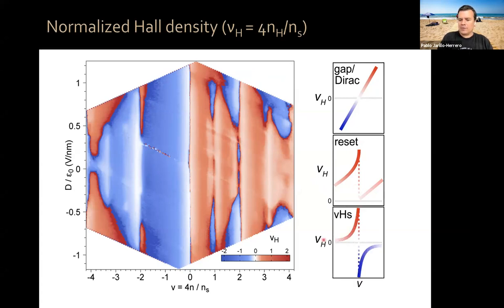And finally, you can have a feature which corresponds to a Van Hove singularity. At a Van Hove singularity, your Rxy goes smoothly through zero, which means your Hall density, which goes as one over Rxy, diverges and changes sign, okay? So you can have something like light blue, dark blue, then abruptly change to dark red, and then to light red, okay? And that's something that, for example, you can see here. You go from light blue to dark blue, then you switch abruptly to dark red, and then to light red, okay? So there's a Van Hove singularity there at that point. There's another one here, and there are Van Hove singularities in various places.